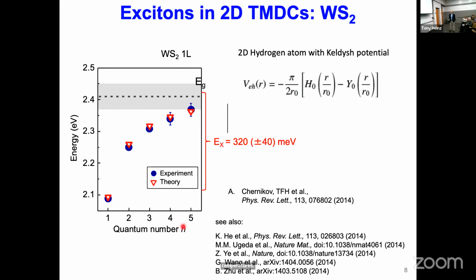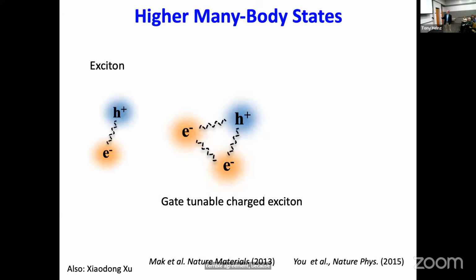If we look at this in a bit more detail, we plot up the energy of these different excitonic states. So these are actually all s states, and since you're creating the exciton, unlike a spectrum of hydrogen where the atom already exists, you see the 1s state, 2s state, and so forth. And if you try to plot them against the two-dimensional hydrogenic model, which I don't show here, you would have absolutely terrible agreement, because the first excited state for hydrogen is something like 85% of the way to the ionization in 2 dimensions.